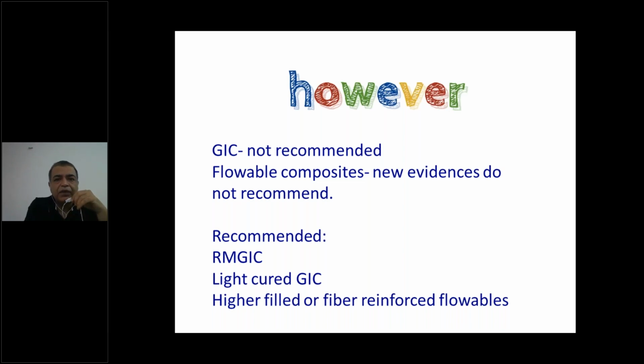The generally available flowable composites should not be used because they have very little filler content and they tend to shrink. If you take my advice, you can use a resin modified glass ionomer or a light cure glass ionomer, or if you want to use flowable, it has to be a high-filler or fiber reinforced flowable composite.